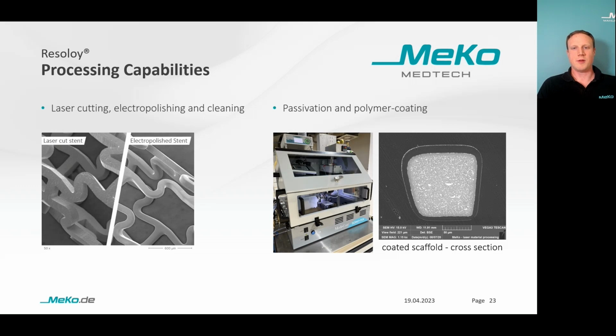Like Laura already mentioned, Resoloy can also be processed like a normal stent material, like stainless steel or cobalt chromium alloy, with laser cutting, electropolishing, and cleaning. We can offer post-processing methods like passivation, and, on an R&D scale, spray coating of bioresorbable polymers with or without drug. You can see here on the right side a cross section of a Resoloy stent strut with a homogeneous coating layer. And in the middle you see the spray coating equipment we have here at MeKo.